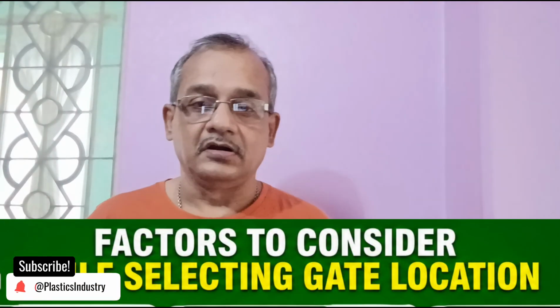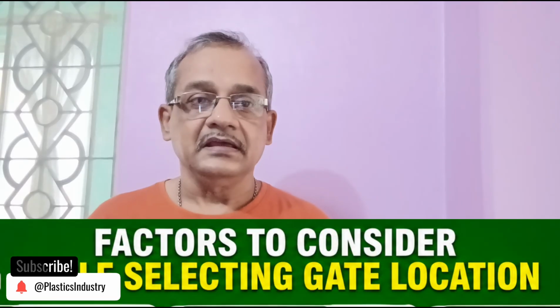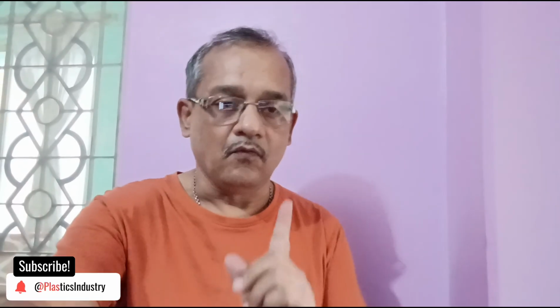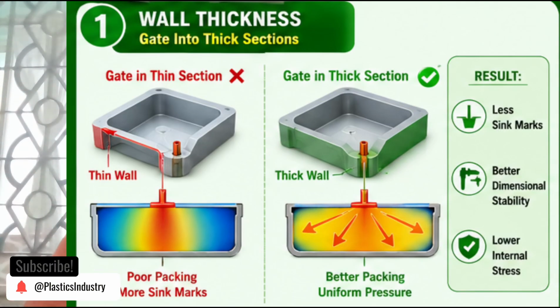Now, factors to consider while selecting gate location. 1. Wall thickness. Always try to gate into thicker sections. Thick sections remain molten longer. This allows better packing pressure transmission.